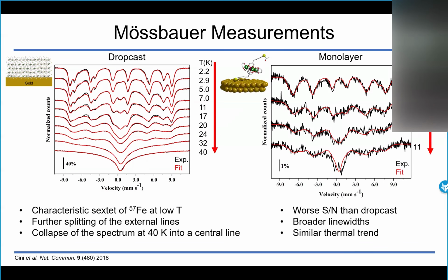So here you can see the Mössbauer spectra from the thick samples that were made as a test of the technique. You can see that at the lowest temperature, 2 Kelvin, the spectrum is essentially a sextet. Then it collapses to a single central line around 40 Kelvin. And here we have the Mössbauer spectra of the monolayer sample. These were the first spectra from a monolayer of molecules. The trend is similar to what we see in the dropcast. Clearly, the signal-to-noise ratio is worse as we have less intensity.